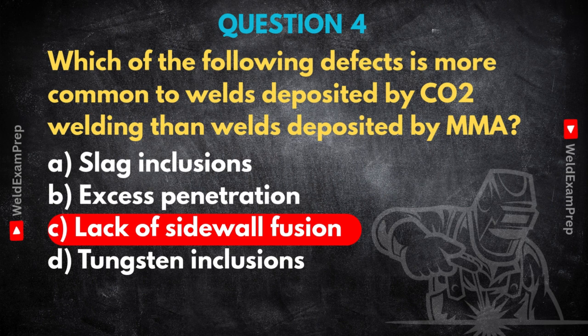Compare that to MMA, stick welding. A really common issue there is slag inclusions. Because you've got all that flux melting, it can get trapped if you're not careful, especially between weld passes. And tungsten inclusions, well, that's specific to GTAW, TIG welding, if the tungsten electrode accidentally touches the weld pool. So yeah, lack of sidewall fusion, definitely something to be vigilant about when inspecting CO2 GMAW welds.